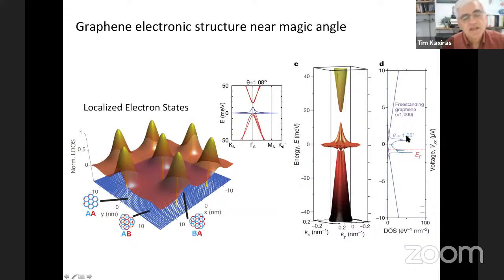So you see this is the density of states at 1.05 degrees. And for comparison, this purple line is the single layer graphene density of states multiplied by a factor of 1,000. So you see how small the density of states coming from graphene itself is, and how big an effect the flat bands are. However, the bands are not completely flat.